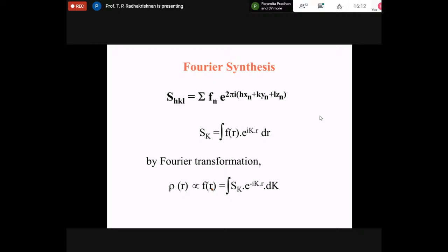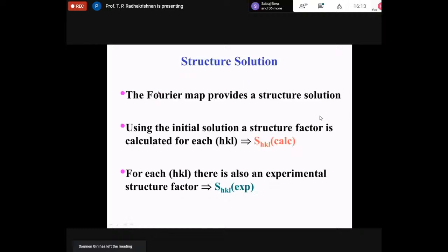Once you get the electron density map in real space, that indeed is your crystal structure, because if I say there is a lot of electron density here, which I can add up to 6 electrons, then I can say there is a carbon atom there. If the electron density adds up to 11 electrons, it will be sodium, atomic number 11, sorry. So depending on the atomic number, you will get the electron density there. Depending on the electron density at different points, you can assign the atom there. So this map of electron density is basically the structure solution. The Fourier map is essentially the electron density in three-dimensional space, which you obtain by Fourier transforming the structure factor. So now you have a structure solution.